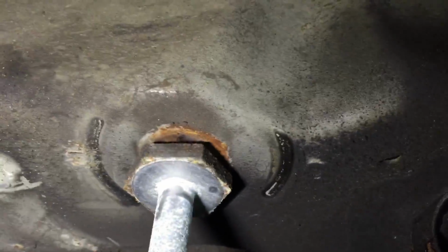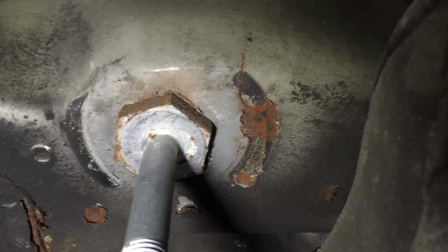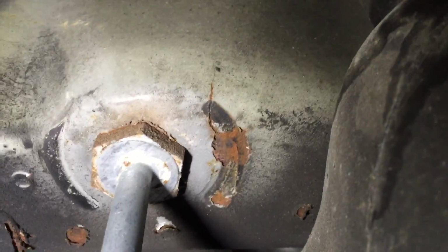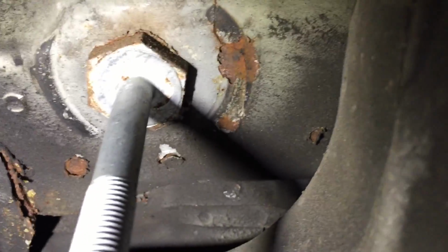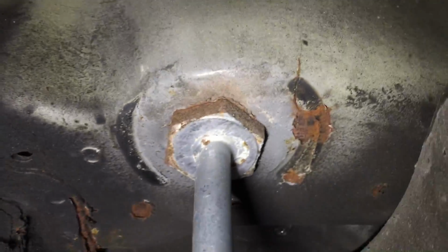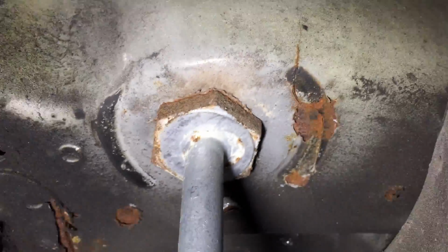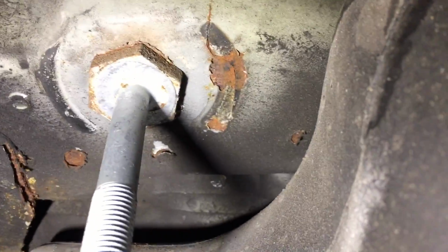Probably got a hairline crack around that bolt there because of the corrosion. We've definitely got the hairline cracks on the spot weld going up vertical and going horizontal across the front section, and probably a little crack around the mounting of that stud as well. A couple of spot welds which are showing flex, which may have broken. Looks like we've got a tiny hairline crack in the fold right in the middle of the screen at the moment. Hard to see with the dirt on there, so we'll degrease that and show you better later on.